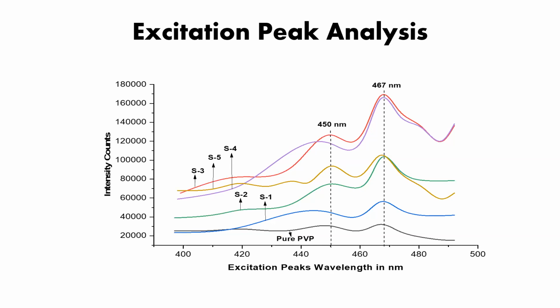here, and on the basis of that, a very interesting phenomenon happens, or these are very interesting calculations. I found that 467 nanometer and 450 nanometer, these two dominant excitation values, can be used for making the excitations to find the emission spectra specifically. But I was also interested in excitation under UV light, because if we excite with UV light, then the purpose of my research goes a little bit higher.